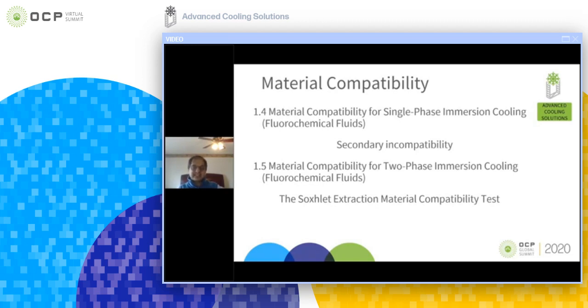So this is called secondary incompatibility, where fluorocarbons merely act as a contaminant vector, because once some hydrocarbon polymer is absorbed in that fluid, it can then be absorbed by another hydrocarbon material. But in the case of single phase immersion cooling with fluorochemicals, these kinds of incidents are very rare. When we talk about two phase immersion cooling, only fluorochemical fluids are available as of now. And the material compatibility is a little bit different because now you are talking about boiling.